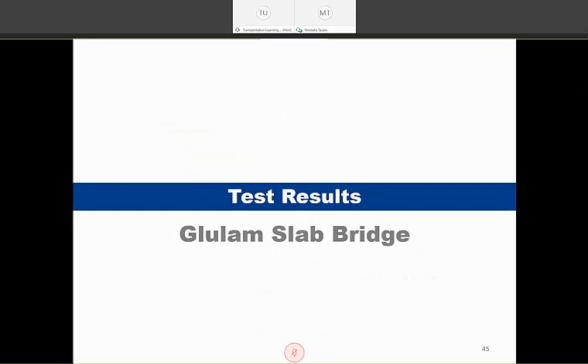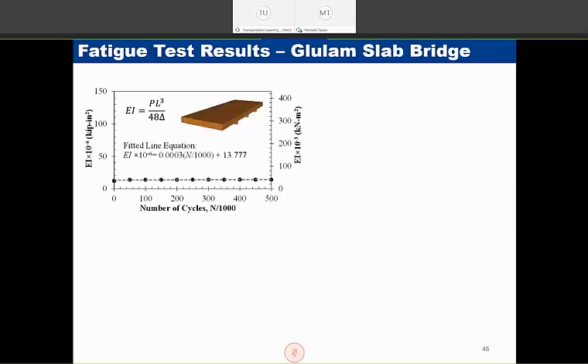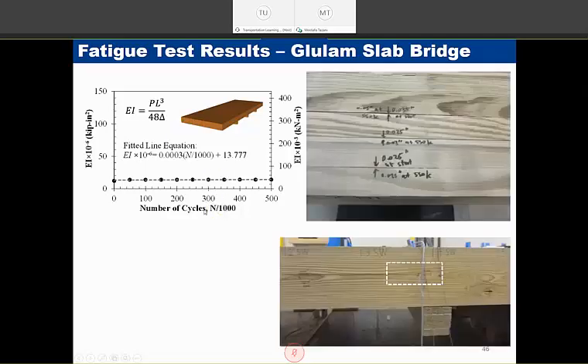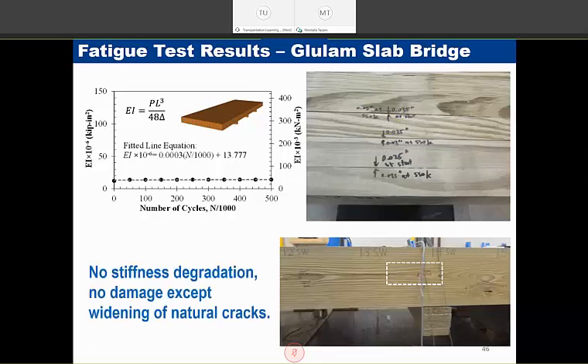And let's talk about the last bridge that we tested, the glue lam slab bridge. Under the fatigue testing, we did not see any deterioration, so the bridge is viable for 75 years of service life. The only damage observed was the widening of the natural or construction gaps. And that was it. For the field application, both of the timber bridges will be flooded at the top at the deck level with epoxy, so you would not see any of these gaps for an actual bridge. For the testing, we did not use any epoxy at the deck level. So there was no stiffness degradation, no damage, except widening of the natural cracks.